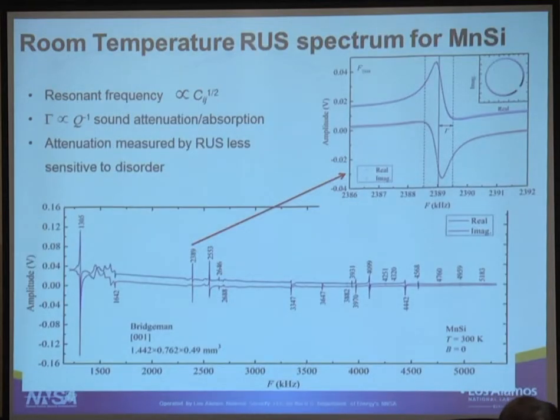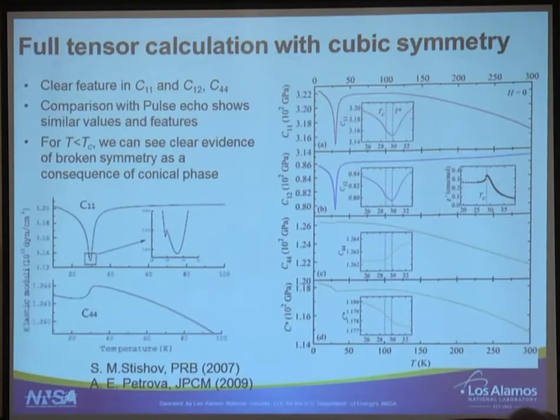Now this is the resonant ultrasonic spectra. So what we do is we measure as a function of frequency. We index each one of the resonant peaks. And then, let's say from 24 peaks that we have indexed here, we are able to get the elastic constants. So here I'm showing C11, C12, C44, and C star. And you say, why? I just told you that we only have 3 elastic constants, and I'm showing you 4.